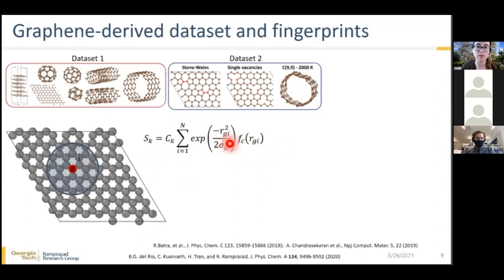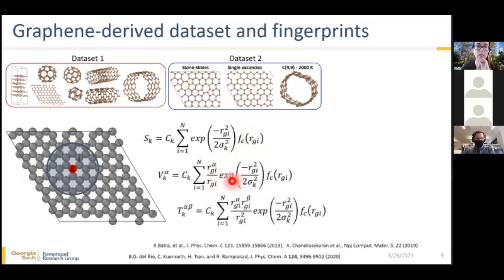Also, to take into account the decay of the effect from faraway neighbors, we introduce a decay function here, which takes the form of a cosine decay and is null after a given radius, which is also another variable that we have to adjust. And similarly, we can define a vector type fingerprint as well as a tensor-like fingerprint, where here alpha and beta are the different components of the vector position of the neighboring atoms with respect to the central atom that is fingerprinted.